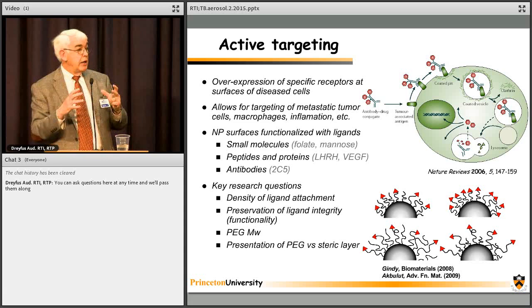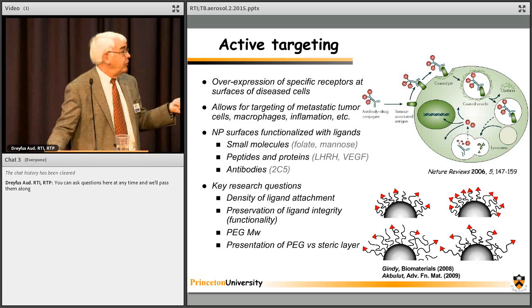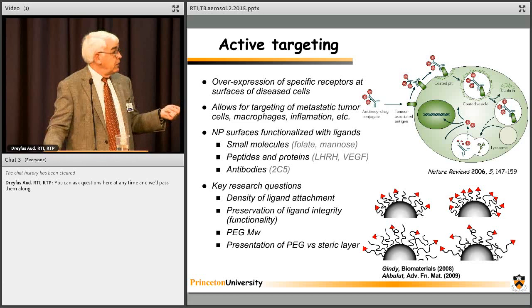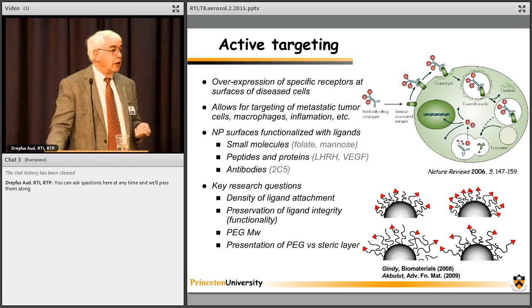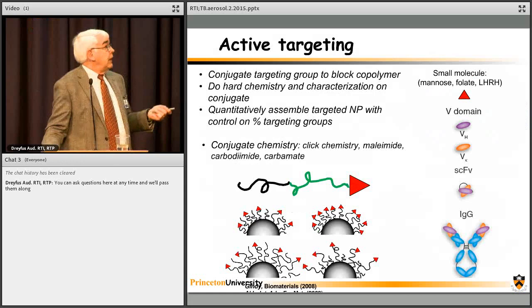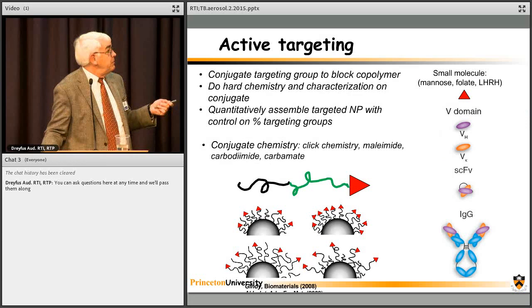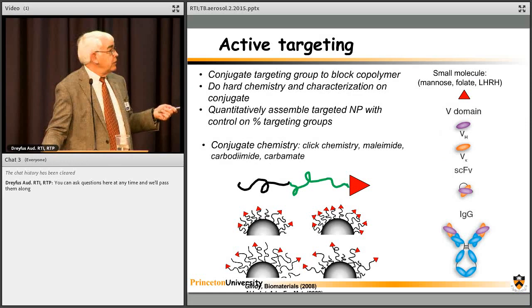Then this picture here is just showing the density. Do we want to go to a tremendously high density on the surface or not? And then this is, do we want the targeting chains to be on bigger chains so they stick out past the steric layer, and is that more effective at them finding the ligand density? We're doing a lot on targeting now from small molecules, and I'll show you mannose targeting for TB, folate. We've gone all the way to antibodies. For us, I think the really interesting region is right in here, single chain antibody fragments.